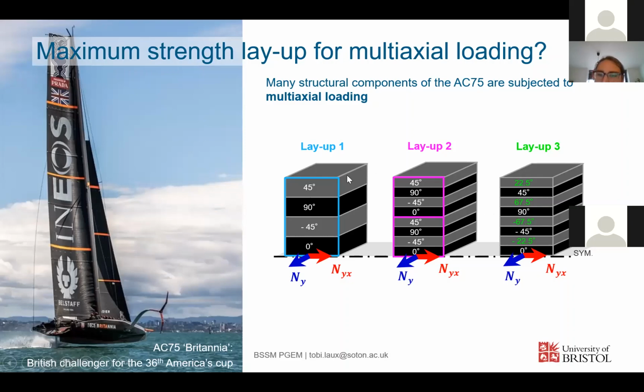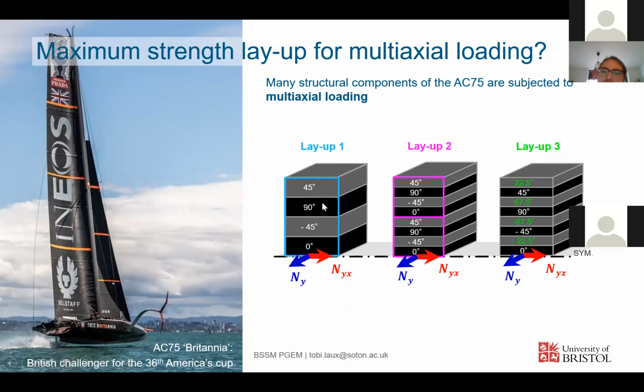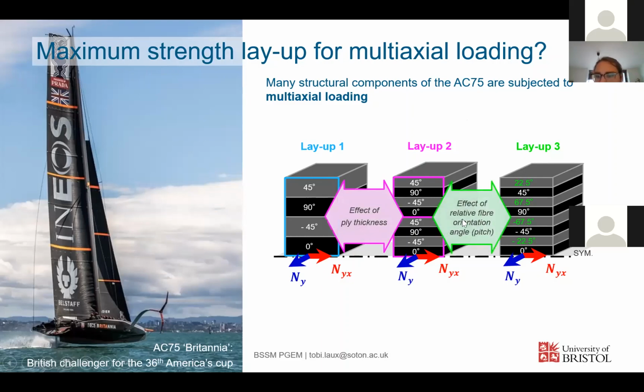By doing this, we also added this layup 2, which is the same ply thickness as layup 3, but the same fiber angles as layup 1. What that allowed us to do is to investigate the effect of ply thickness, as well as the effect of the different fiber orientation angles.